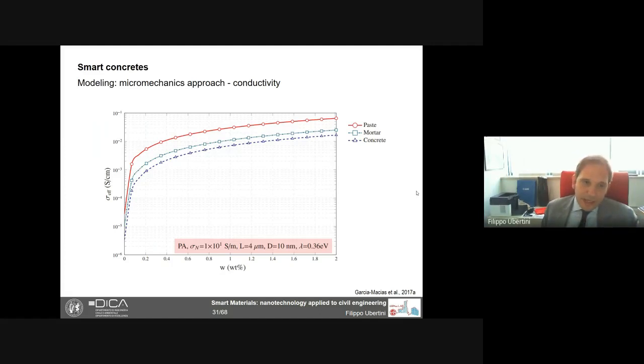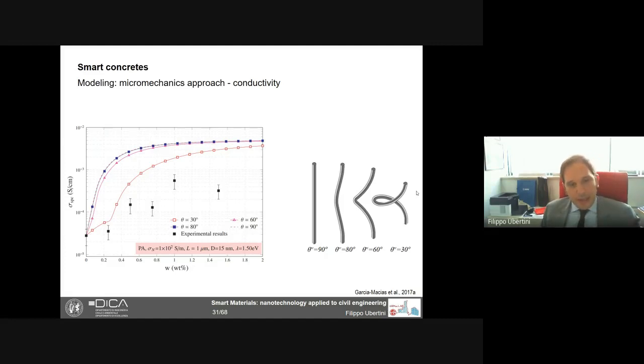And these are typical results we get in terms of effective conductivity as a function of content of nanotubes for paste, mortar, and concrete. You see that there is this percolating behavior. But if we compare this with experiments, and experiments are the squares in this diagram, we do not really get a good match, even if we introduce the twisting of the nanotube. So we go from the purple line to the orange one, changing the angle theta from 90 degrees, that means straight nanotubes, to 30 degrees, that is very twisted nanotubes. Still, we do not really get close to the experiments. We get closer with twisting of nanotubes, but not really close.